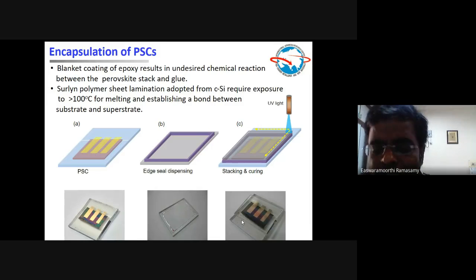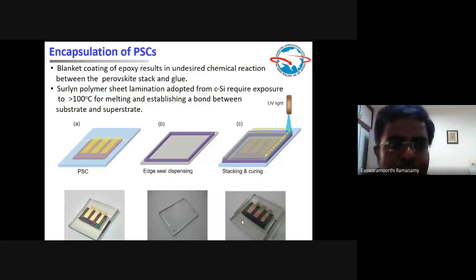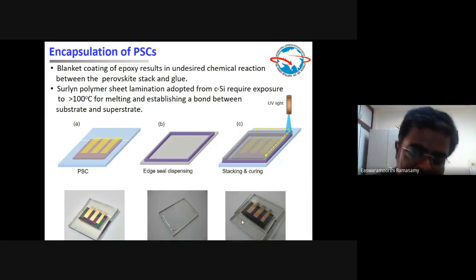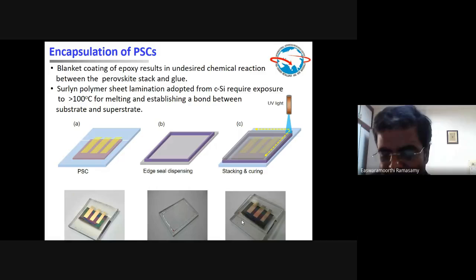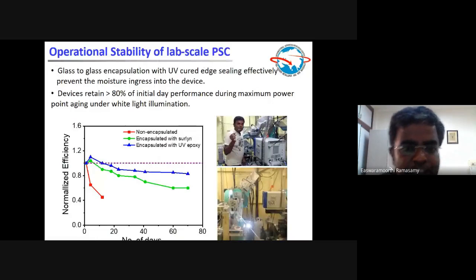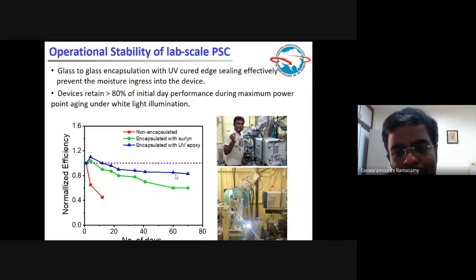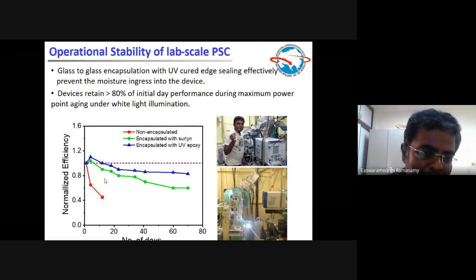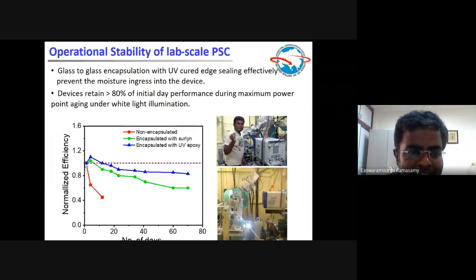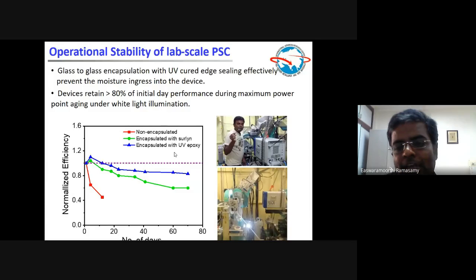Normally people use the conventional approach, but perovskites are not stable at high temperature, right? So we have to use a low temperature approach. That is the technique behind it. It's a low temperature encapsulation. So we made the device with no encapsulation, with conventional encapsulation with high temperature application, and with our own developed low temperature epoxy encapsulation. You can see this is the degradation trend. We were able to improve the stability of the device by our low temperature encapsulation approach.